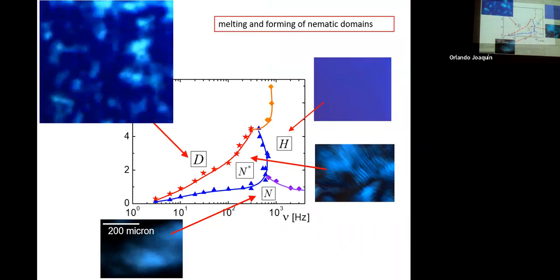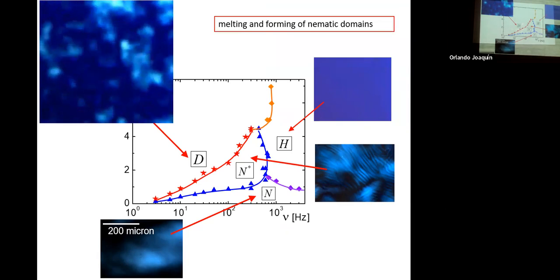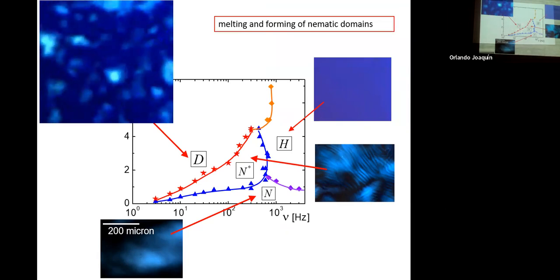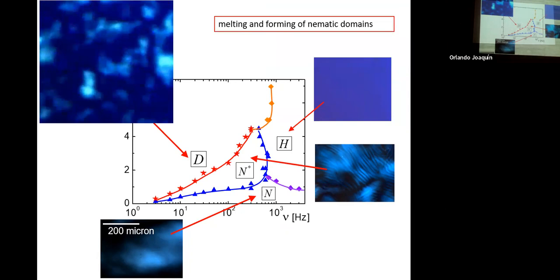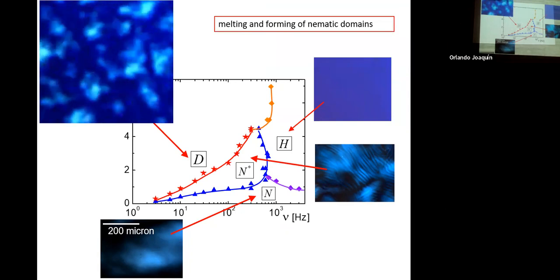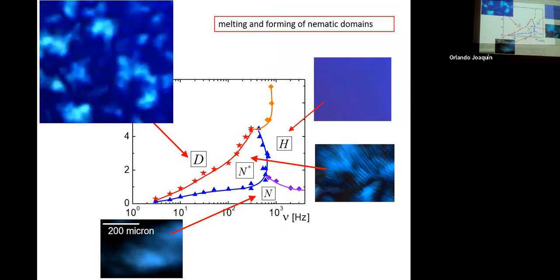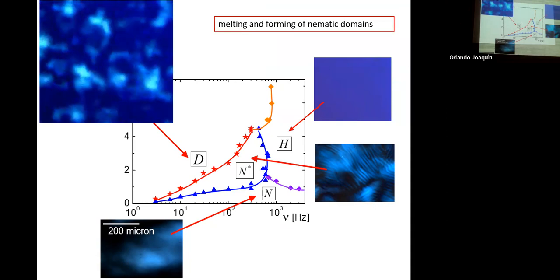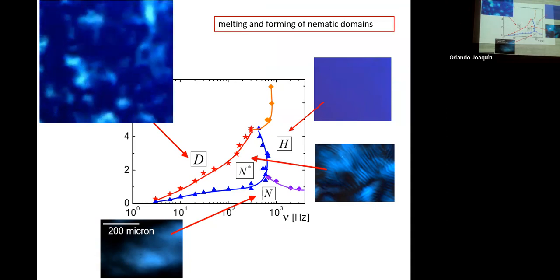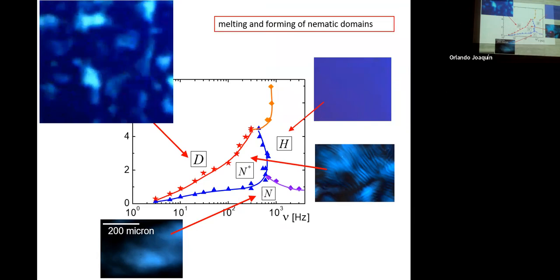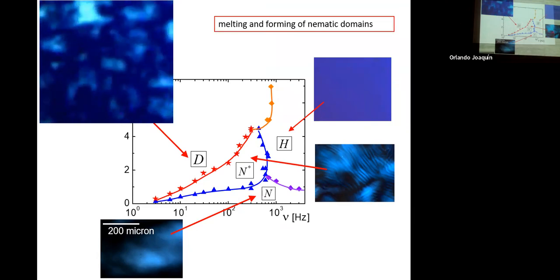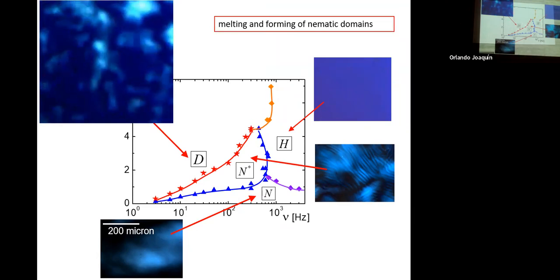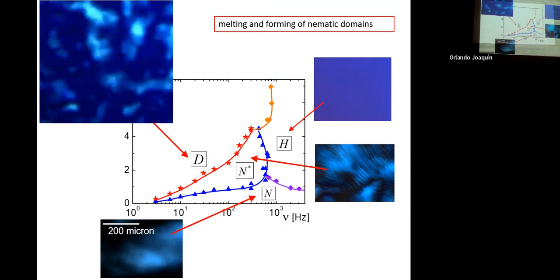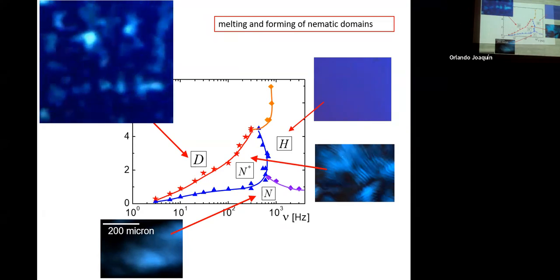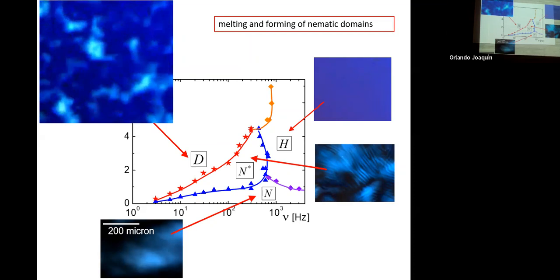Now, the most interesting thing is that if you go along this line here, you will enter a so-called dynamical state where these nematic domains melt and form all the time. Now, of course, this is a static phase, so it doesn't change in time, or hardly. But as soon as you cross this line, these domains melt and form. I'm going to explain in a minute why that happens.